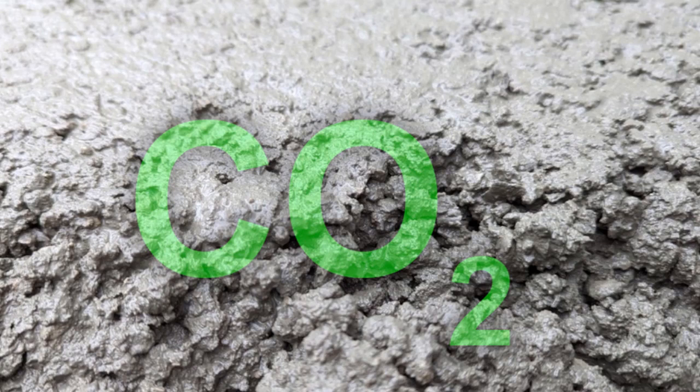In lab tests using sodium bicarbonate substitution, the team demonstrated that up to 15% of the total amount of carbon dioxide associated with cement production could be mineralized during these early stages, enough to potentially make a significant dent in the material's global carbon footprint.